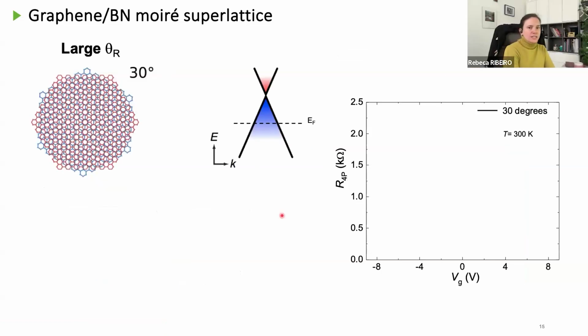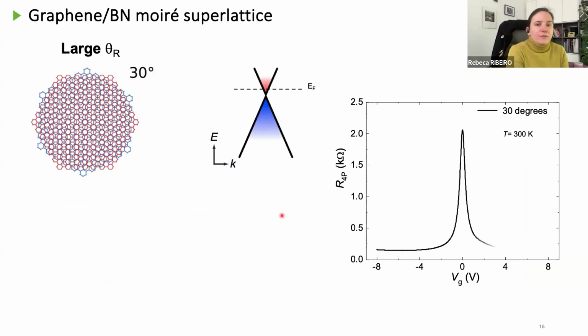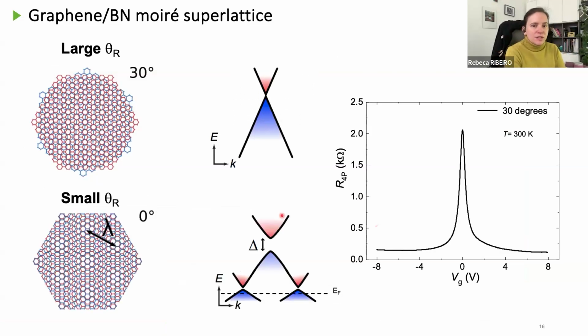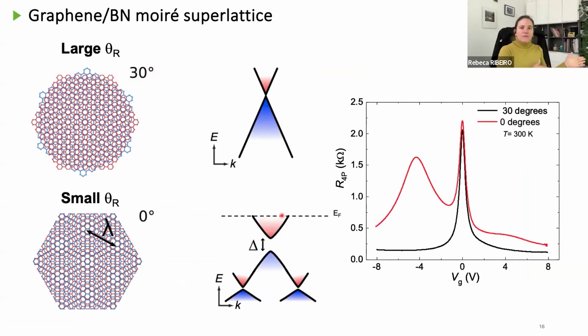Okay, so we were talking about moirés, and now we know what's the transport response, the electron transport response for a fully aligned, that is 0 degrees alignment, and for a 30 degrees alignment graphene. Okay, so this is very beautiful. We have a modification of the electronic band structure. Please remark that these measurements are made at 300 K, which is room temperature.